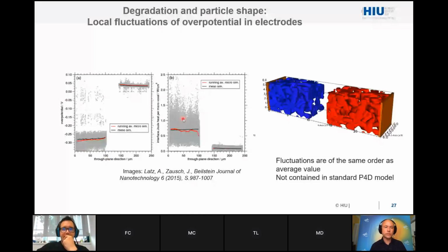But there remained a huge scatter, and this is really huge. If you see here, this is a volt. So we have here minus 0.3 volt, and we have scattering events going up to 0.1 volt, so changing the sign, going up in voltage. And this means in the overpotential, you have enormous fluctuation. And if you think that SEI growth, for example, or plating is something which is going to happen locally, then these fluctuations are of enormous importance, but they are not captured in the standard P4D model.